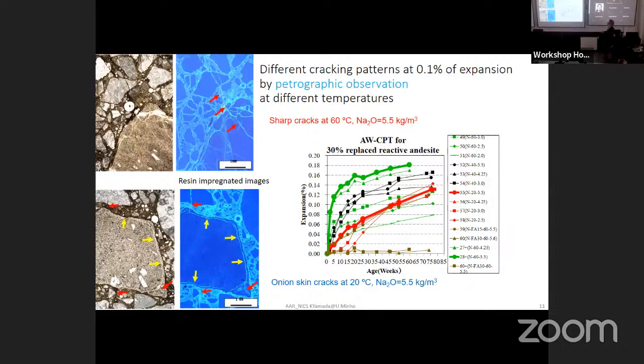My colleague at university carried out many experiments at different temperatures. The 60 degree results are the green lines. Alkali content was modified from 2 kilo to 5.5 kilo. At 60, more alkali results in more expansion. This is the reason. But at 40, indicated by black lines, no effect of alkali content was detected from 3.0 to 5.5. There is no effect of alkali content.